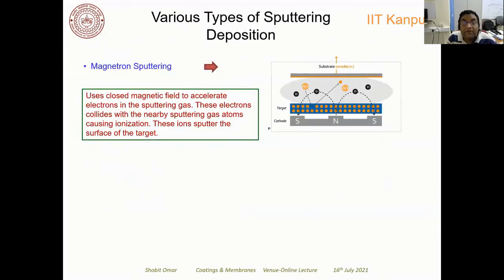Now, there are different types of sputtering deposition techniques, and I just listed a few of them, but you will appreciate that there may be different variants of sputtering deposition techniques people have used. First one is magnetron sputtering, and you can see that the target is here, right? This is a target and this is a substrate. Below this target, you have magnets present, which is basically called the magnetron. What they do is that the electrons present in the sputtering gas or plasma, they try to attract these electrons and move them in a cylindrical path.